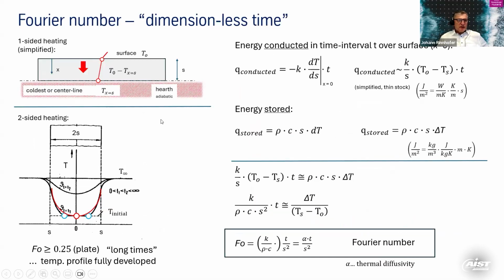Look at the Fourier number. We talked about Biot before, this is the thickness, and now we talk about the heating time. The Fourier number gives us the dimensionless heating time, so to say. What does that mean? Now we look just at the inside of the body. We don't look at the outside, so no external heat transfer anymore. So we say the conducted heat in the body is this expression here, the thermal conductivity divided by S, the thickness, times the temperature difference from the surface to the core, times the time we are heating.